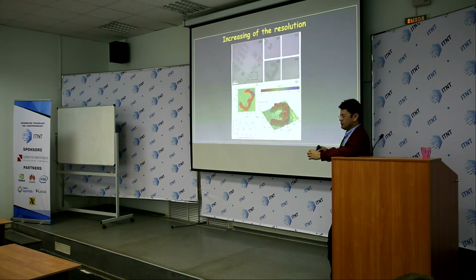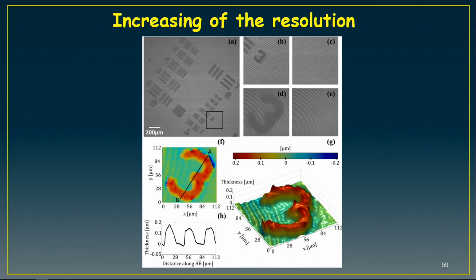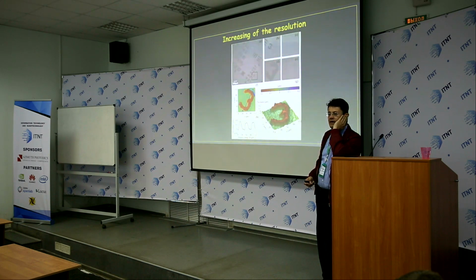But there is some information we can get. For example, in our laboratory, we analyzed the morphology of red blood cells using the interferometric microscopy technique. Red blood cells have a donut shape, and we have found that some conditions, for example fatty blood and blood with sugar, change the morphology of the red blood cells, depending on the amount of fat inside the blood. So we can analyze the morphology changes in blood in comparison with healthy blood, and get more information in comparison with ordinary optical microscopy using the interferometric 3D microscopies.